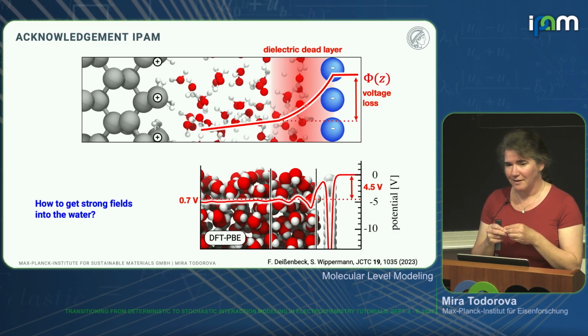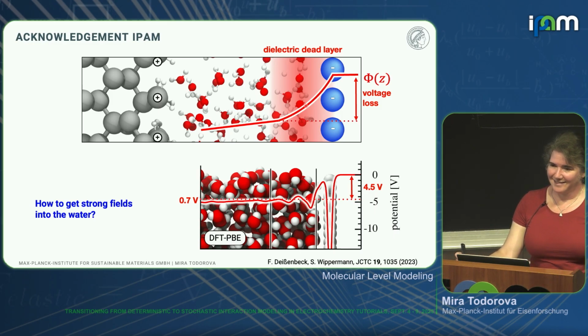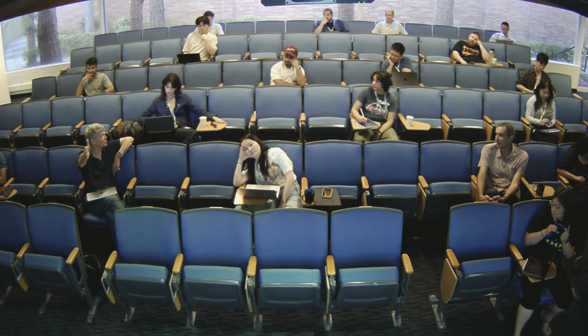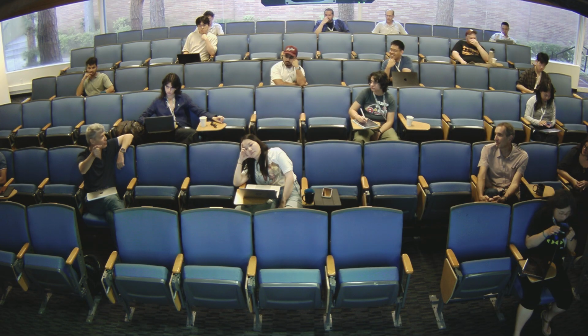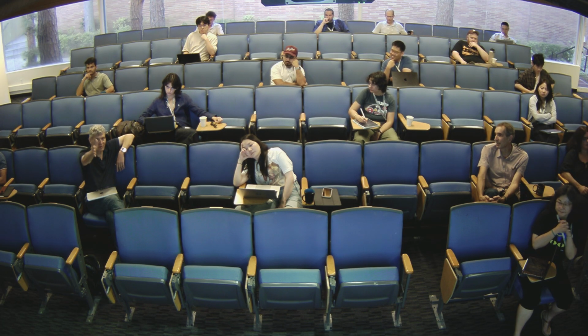I find the idea very interesting, but you have also to remember, this has to be a semiconductor, a wide bandgap semiconductor, and a closed shell system. So this really makes it, from its nature, very hydrophobic, because there is no interaction. And what we typically find, even for magnesium oxide, which is super reactive, is that the gap is still rather large there. So there are a few water molecules that are chemisorbed, but you don't really get a close contact with the water. And then it's simply a matter of numbers.